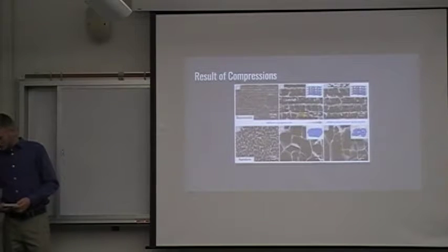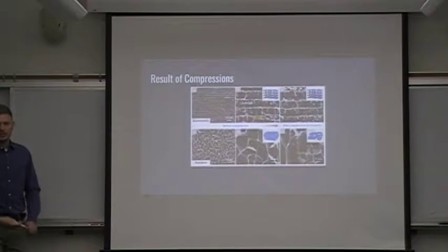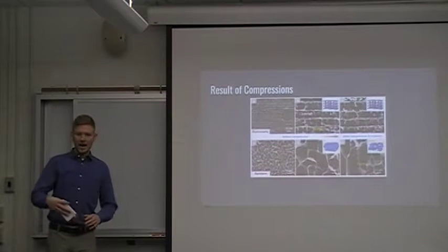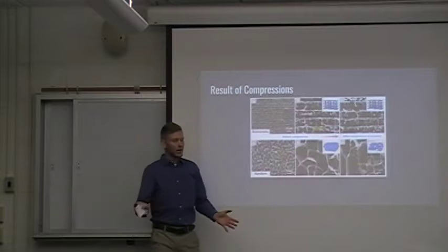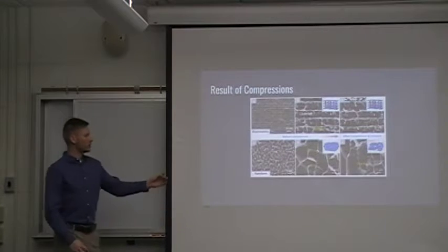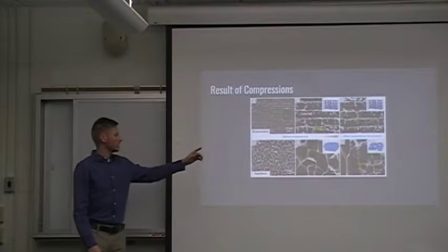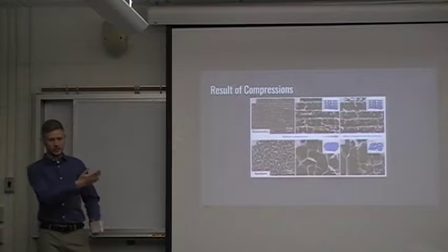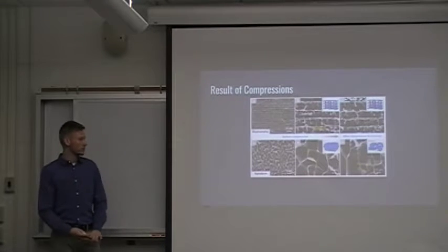And this is an after look, a scanning electron microscope image of the graphene aerogel after the compressions. Notice how this has no obvious changes aside from minor fractures in the bridges, but as noted in the graph, that doesn't make much of a difference because there's so much support there for the aerogel.